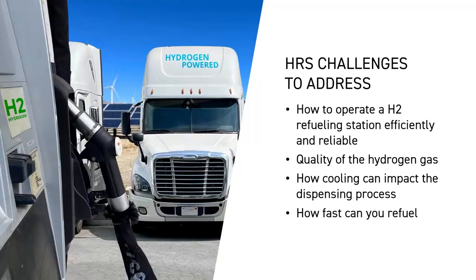How cooling can impact the vehicle dispensing. Where most gases cool down when pushed through an orifice, such as the refueling dispenser nozzle, hydrogen actually heats up because of a thermodynamic property known as the Joule-Thomson effect. If not controlled, this could lead to overheating, which basically the composite material used inside the construction of the high pressure hydrogen fuel tanks could overheat. Those tanks are not supposed to see temperatures above 85 degrees Celsius.